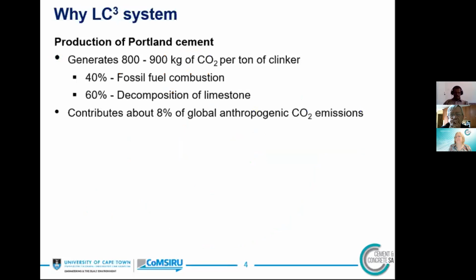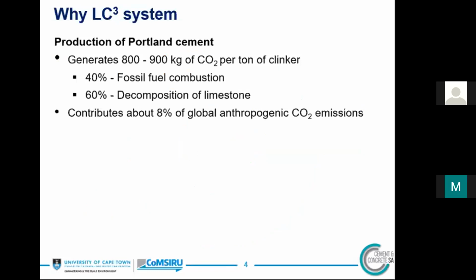So why do we need this system? We all know that the production process of Portland cement generates about 900 kilograms of carbon dioxide per ton of clinker. Fossil fuel combustion is responsible for about 40%, and the decomposition of limestone is responsible for the rest. So for environmental reasons, the use of clinker must be minimized so as to reduce carbon dioxide emissions. Currently, it is estimated that the production of cement contributes about 8% of global anthropogenic carbon dioxide emissions. And about 40% of cement that is produced globally is used to make concrete.